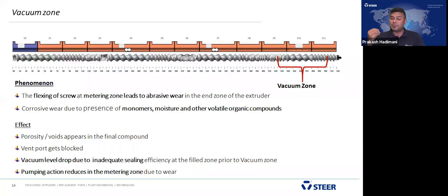Corrosive nature comes in the vacuum zone because of some unreacted monomer during the polymerization. If you didn't apply vacuum and remove it completely, then the unreacted monomer adheres, and also some moisture and volatile organic compounds cause corrosion in that section. What is the effect that happens?